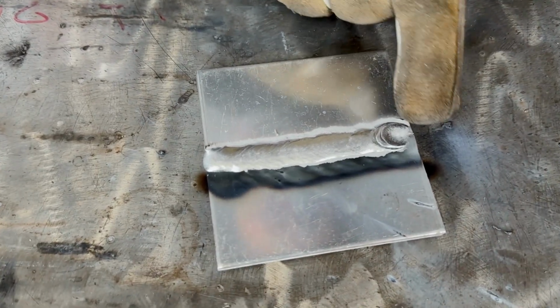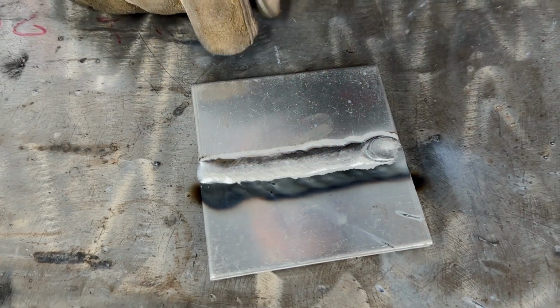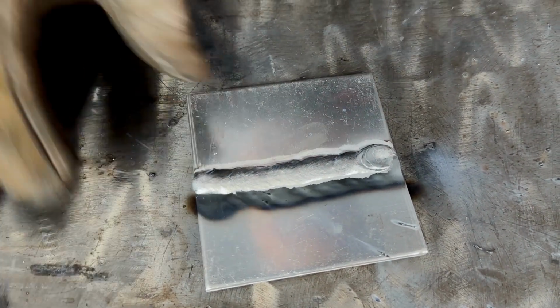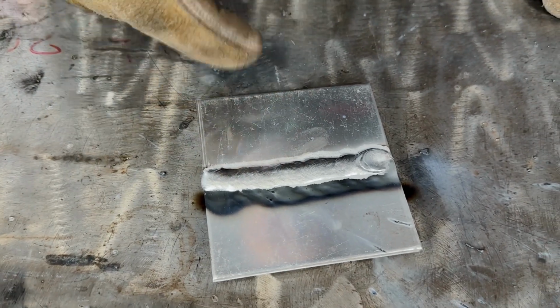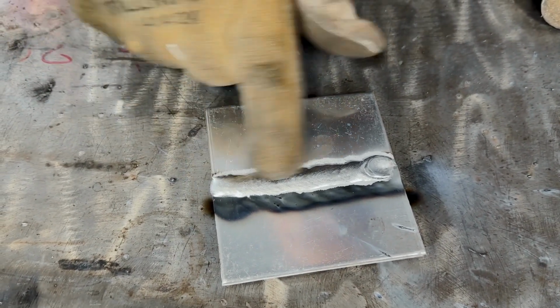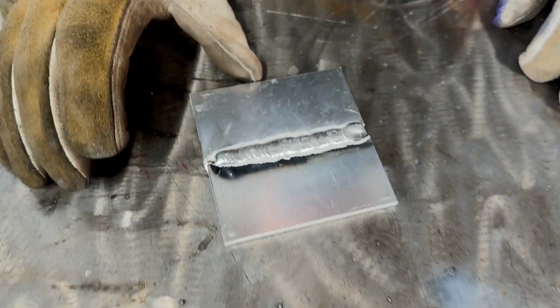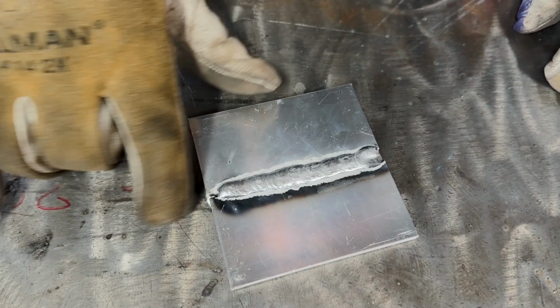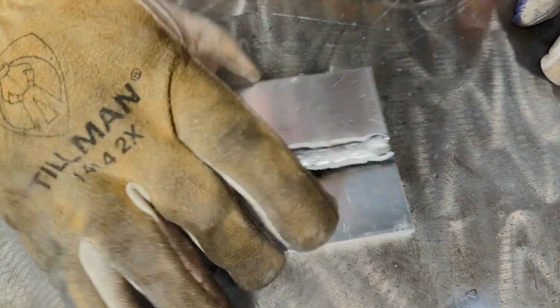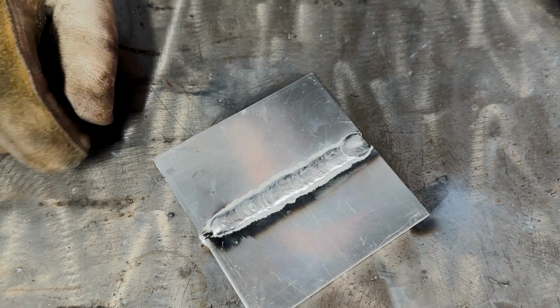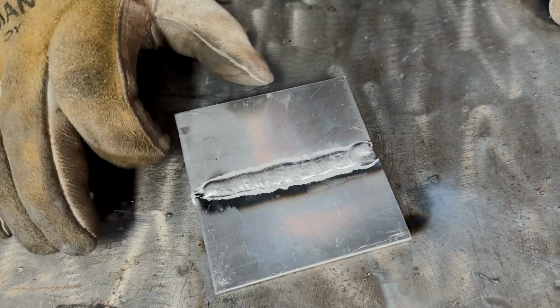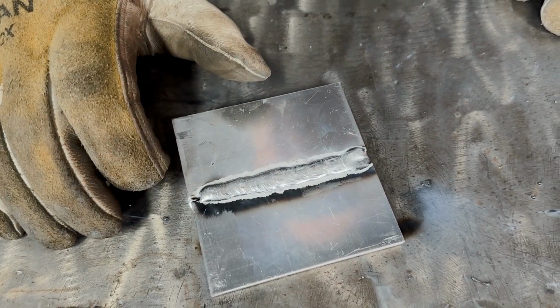So I gave it a couple extra squirts at the end and the crater is gone. You can see the bead is much wider and cleaner. That's because this entire piece was now naturally preheated because it's the backside of what I just welded. So you'll have deeper penetration and probably you can see it even coming through here on the startup, on the cold start, which was here, but the piece was preheated. So you see some bleeding through right there. So this is probably pretty close to a full penetration weld, if not a full penetration weld.